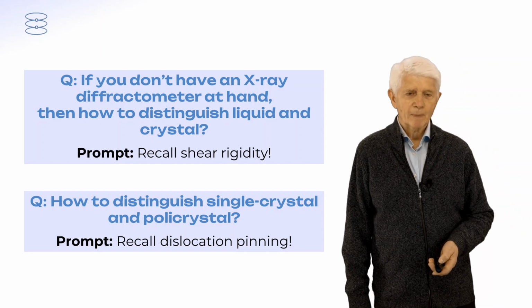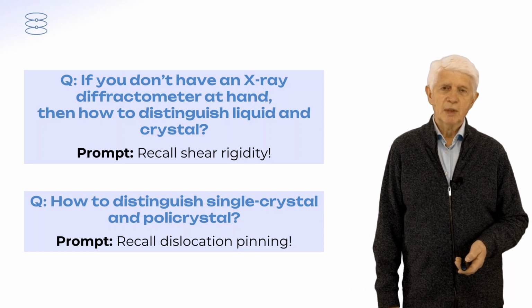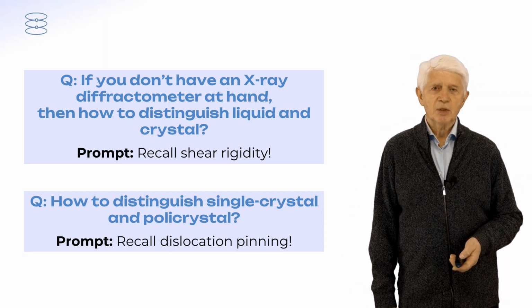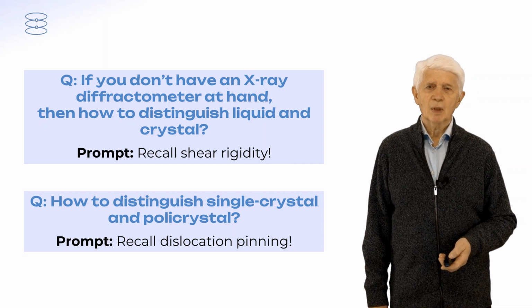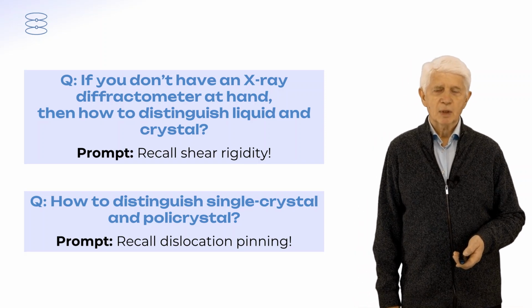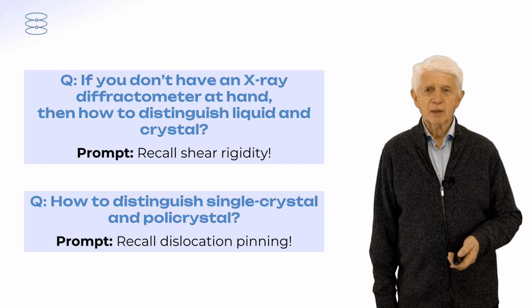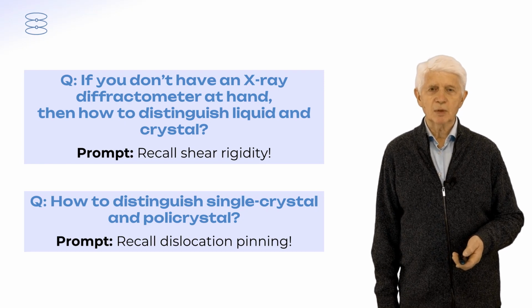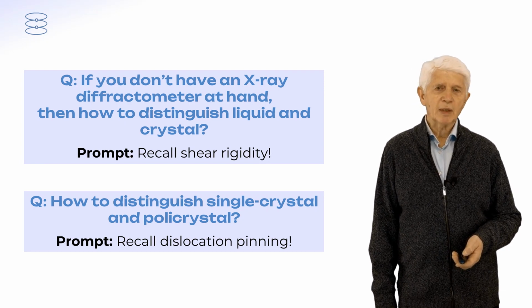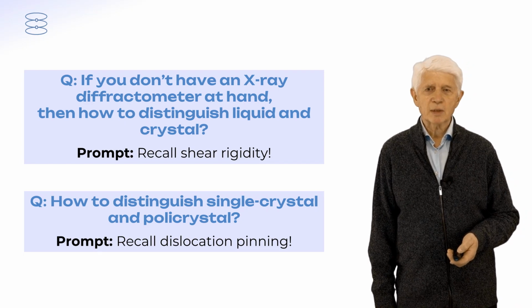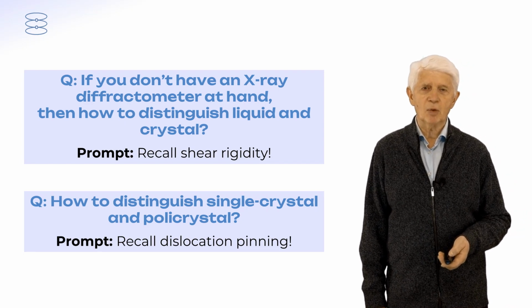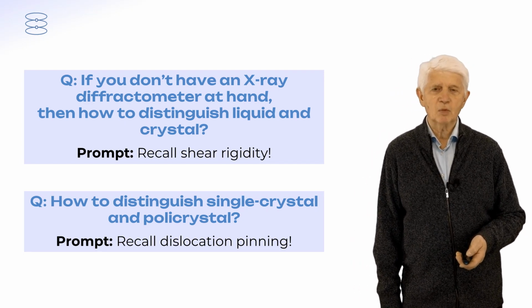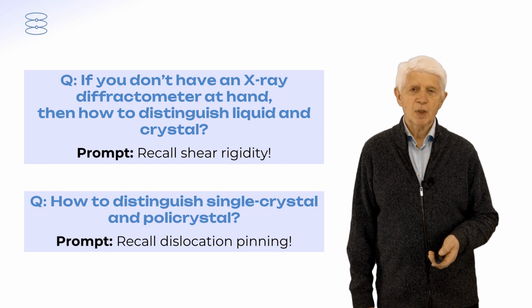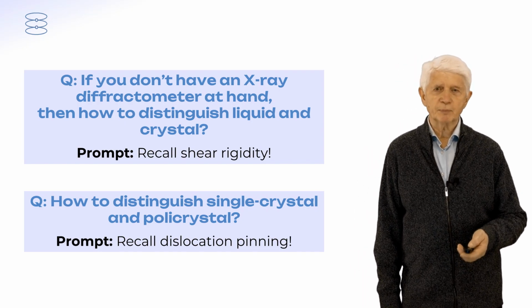When you're trying to deform a single crystal, you can hear with your ears the sounds related to the entrance of dislocations into the single crystal. On the other hand, the polycrystal already has a lot of dislocations, and therefore its bending, its deformation will not be associated with the acoustic emission.